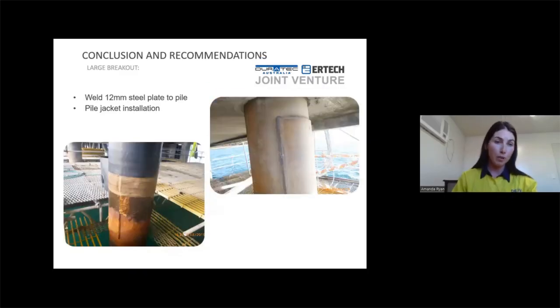So for larger breakout areas, we once again broke back the concrete to the bare steel, and this time the steel was that deteriorated that we couldn't just apply the zinc-rich primer. We had to do further repair methods. So we had to steel strengthen the pile. We installed a 12 millimeter steel plate to the pile, which is this. It's the radius of the pile, and fully welded, 8 millimeter fully weld on every side. And then over that, we installed the pile jacket.